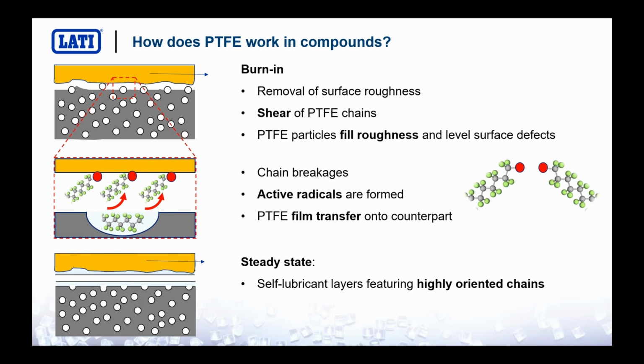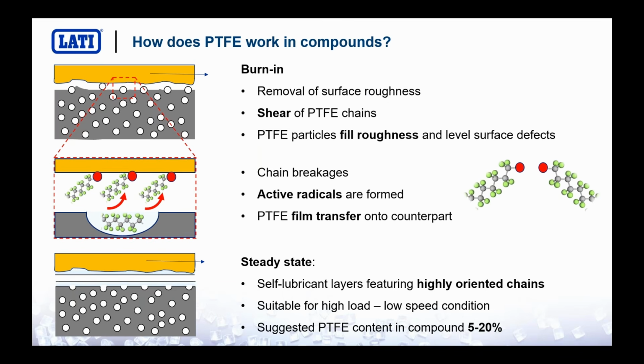so with very highly oriented chains. So a very good situation due to the properties that we mentioned in the previous slide. PTFE works in a very good way, above all for high load and with low speed. And the typical percentage of PTFE in the compounds goes from 5 to 20%. So the secret is this film transfer that we try to obtain also with other polymers, as we can see in the next few slides, to take advantage of it.